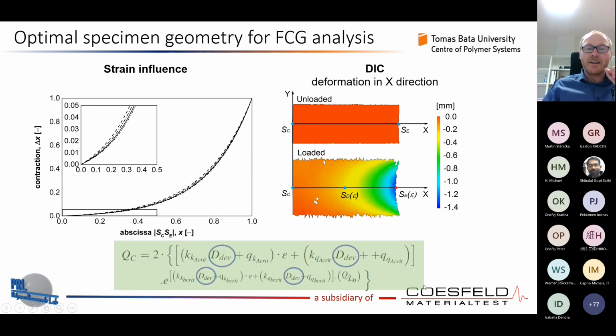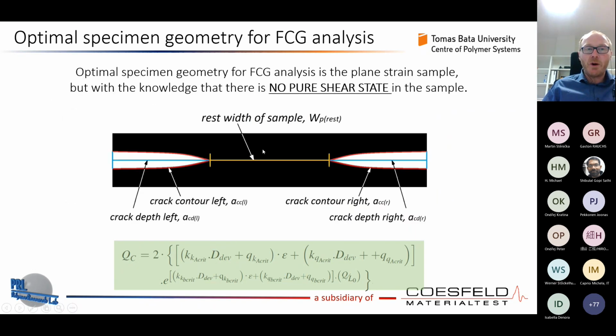There is one parameter, the deviation d, which is in this equation. This deviation parameter describes what we allow, how big the deviation from the pure shear region can be. For example, as I denoted here, if we allow 20% deviation, then we will have the 20% here, and we can calculate how big the pure shear region will be with this point, and so on. And that's a very important point.